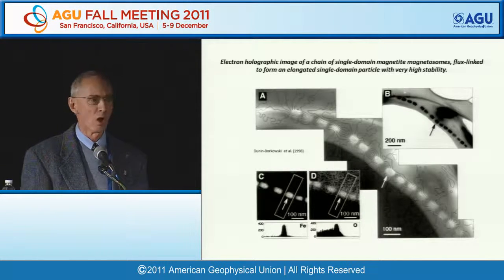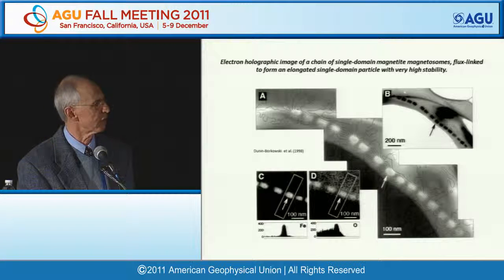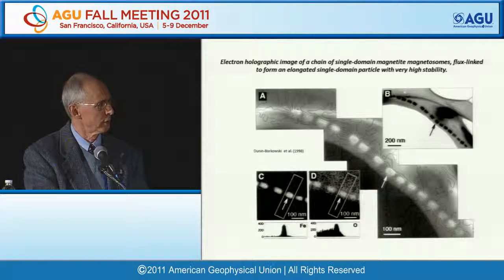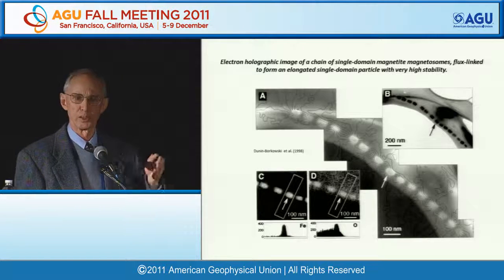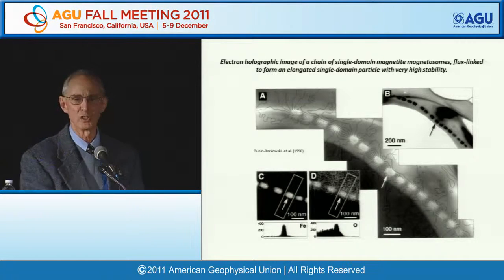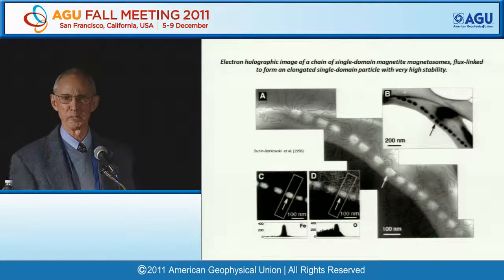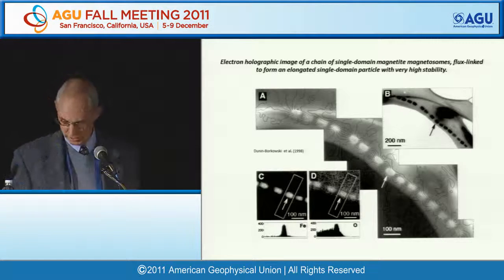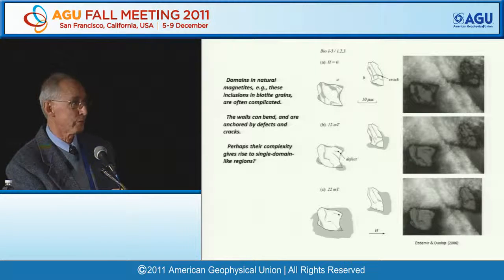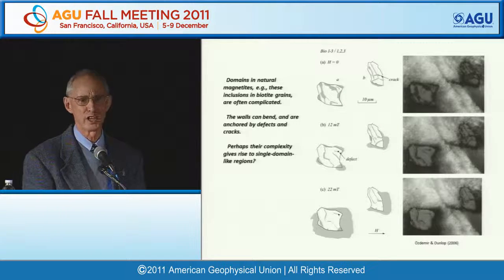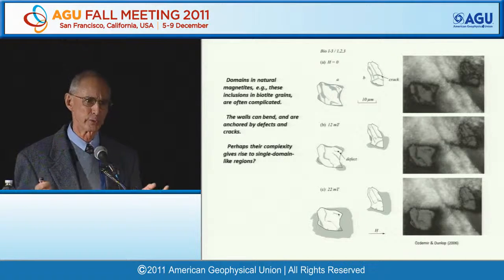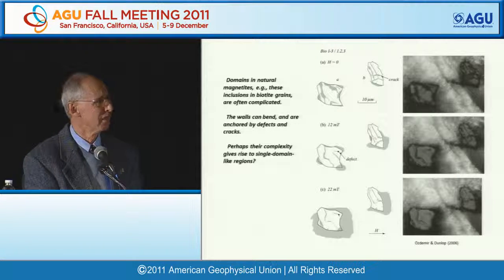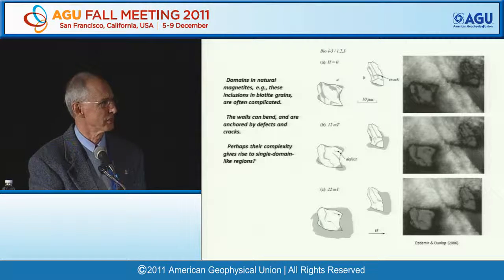If you look at the very small end of things, which Dunin-Borkowski et al. have done here using electron holography, at single domain particles, you can find those too. These magnetosomes are individually single domain. They're also linked together, flux linked along a chain to produce an elongated single domain particle. They're out there in nature, but if you just go at random and pick up your average kind of dirty magnetite from dirty old rocks that we do paleomagnetism on, you find something considerably messier.